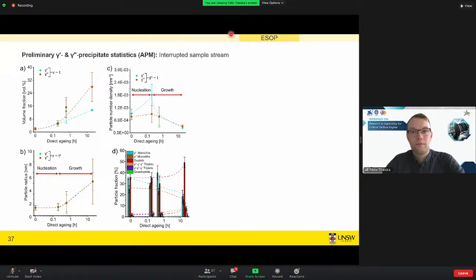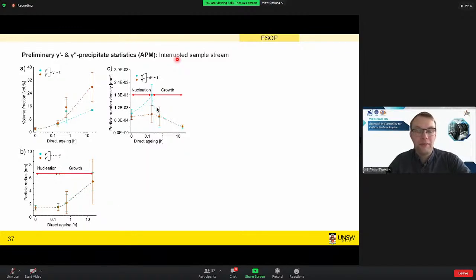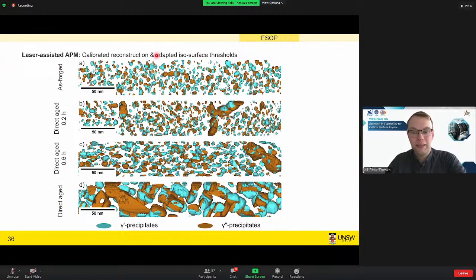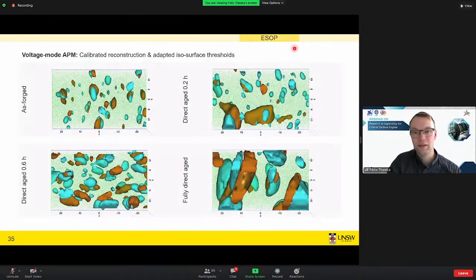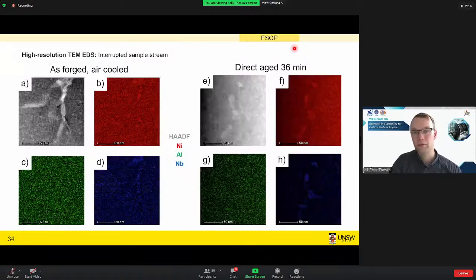So in general, Felix, I want to ask you, which one is more accurate for identifying the elements: the atom probe microscopy you displayed, or the EDX from TEM? Both are accurate, right? But atom probe has a really high signal to noise ratio, so we can quantify very low amounts of these alloying elements. For example, here I'm able to identify these particles in the as-forged condition, whereas if we look at the TEM EDX, we don't get a very clear signal here. But if we have any larger structures, then both become feasible.